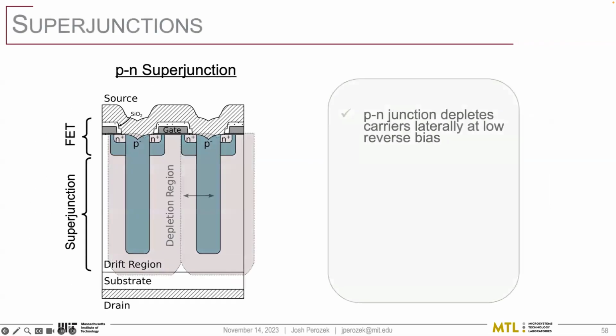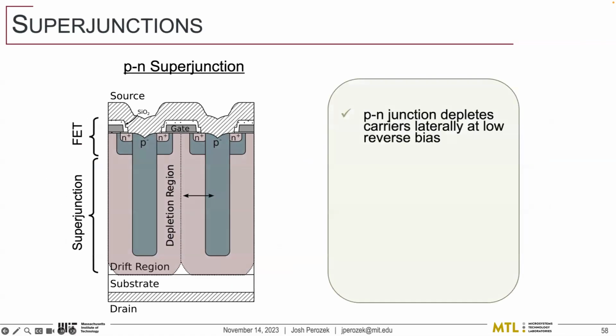So then how do they work? For our normal 1D unipolar devices, to establish an electric field that lets us have a high breakdown voltage, you have to remove all of the electrons from the device. This is done by the drain voltage. As you ramp that up to 1,000 volts, it makes a very large depletion region that depletes your whole epi layer. And you aren't able to remove all those carriers until you're essentially at breakdown voltage.